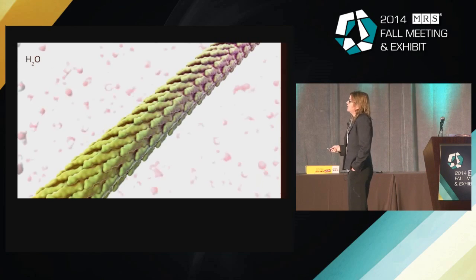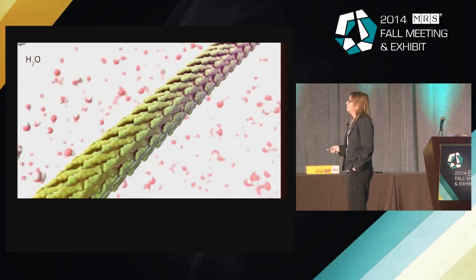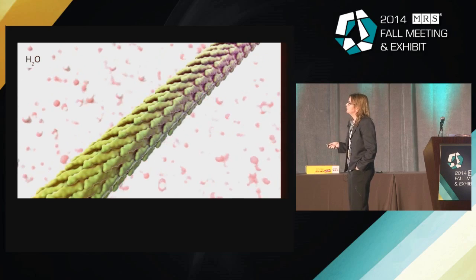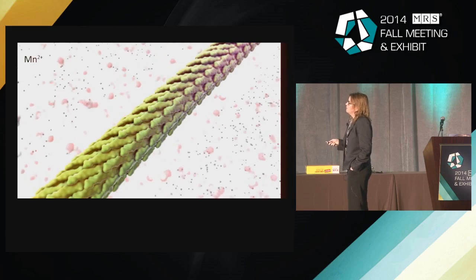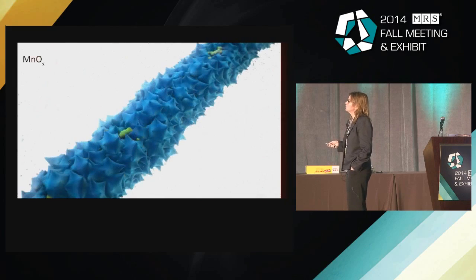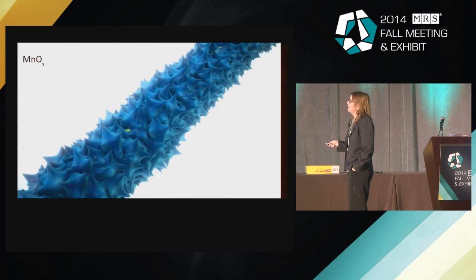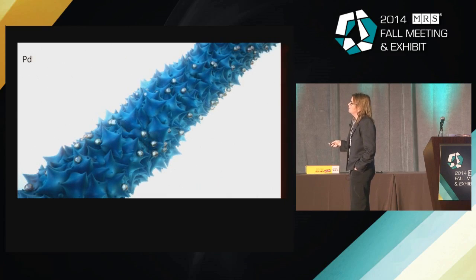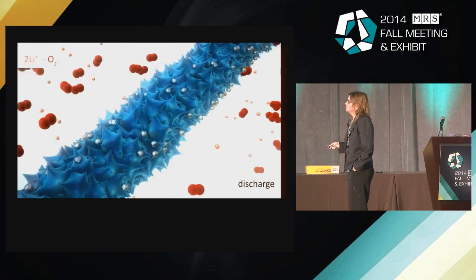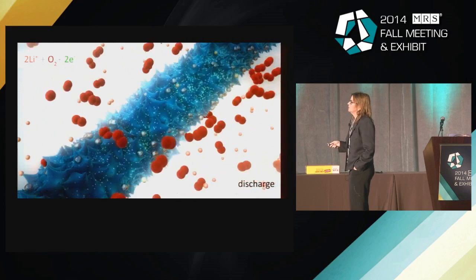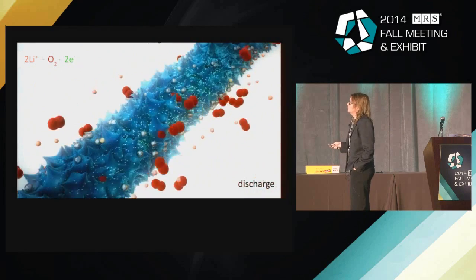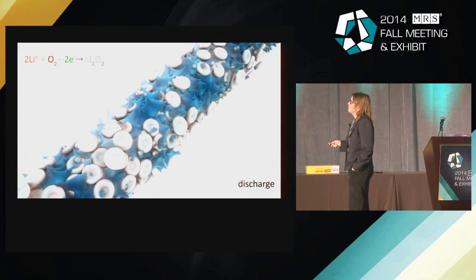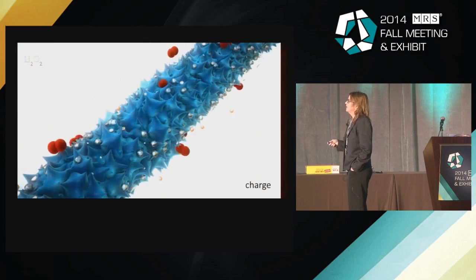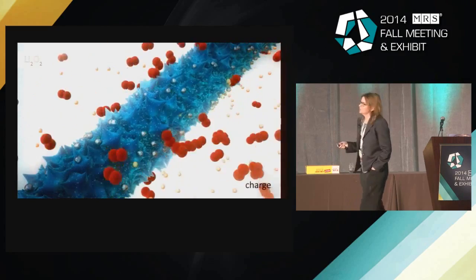And this is a movie that she made where basically you have a virus, it's in water. It has the sequences to be able to grow a manganese oxide material. And you give it a manganese ion source, and you grow these manganese oxide, these very spiky, high surface area materials. Now we give it a second ability to be able to bind palladium, and then you can test it as an electrode material: lithium plus oxygen plus 2 electrons forms lithium peroxide, and it's a reversible reaction.